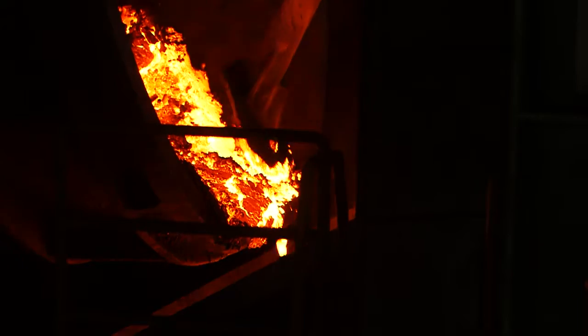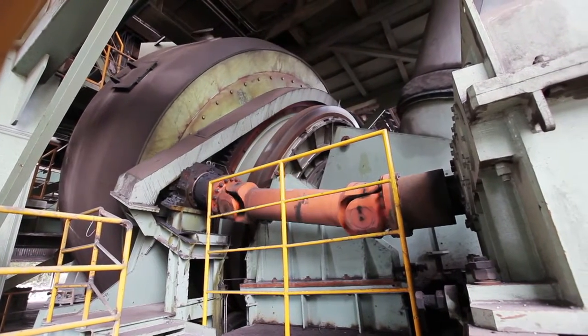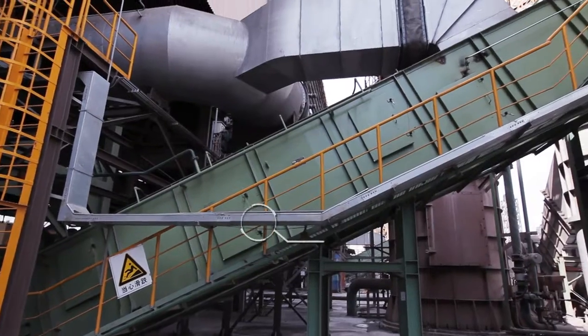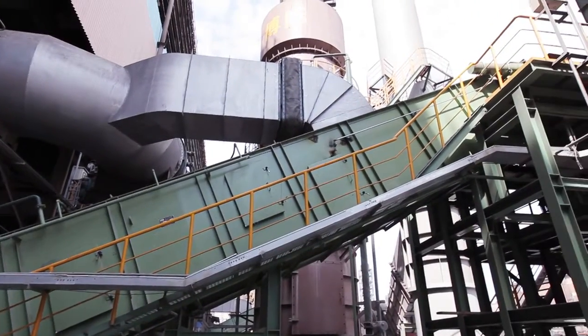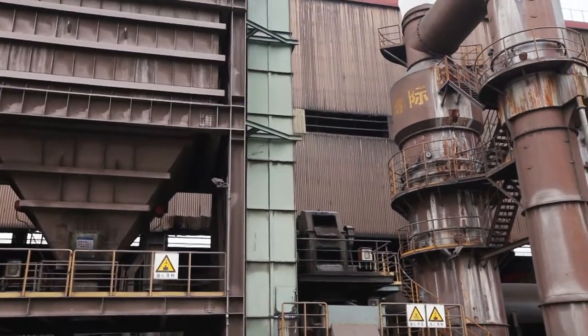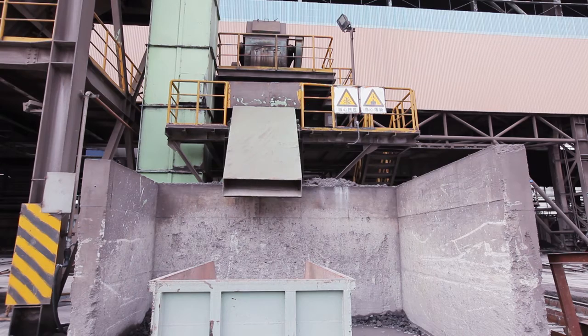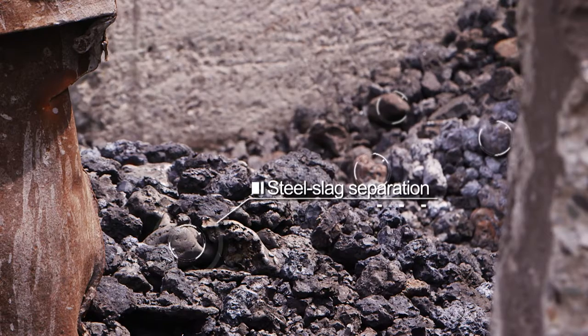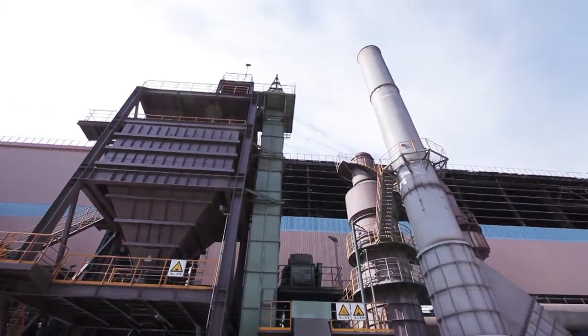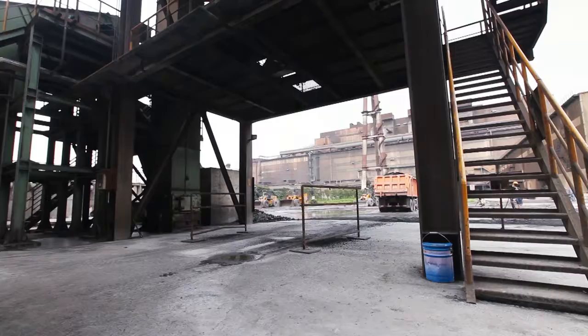Slag after processing turns into less than 70 mm particles; over 70% will be less than 10 mm solid slag particles. These are discharged from the slag drip opening of the drum, fall onto the combined conveyor, and transferred to the bucket elevator. A vibrating screen is set between the combined conveyor and bucket elevator to screen out a small amount of bulk steel and slag. Most of the slag will enter the bucket elevator to the high-level feeding storage bin and finally transported by truck.